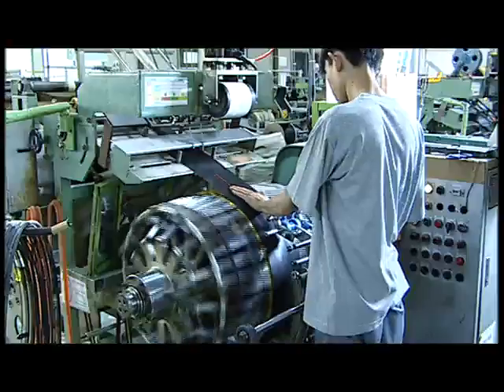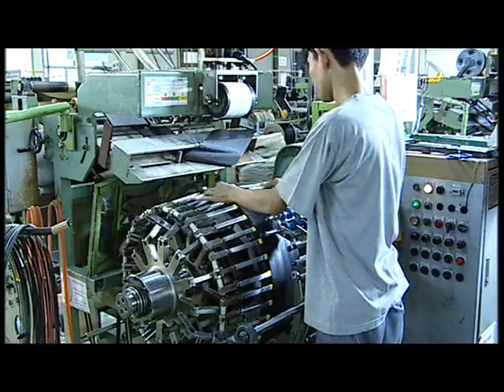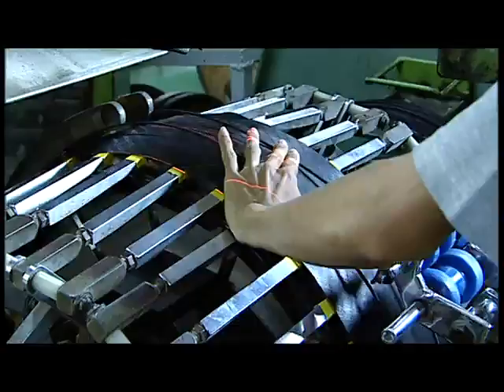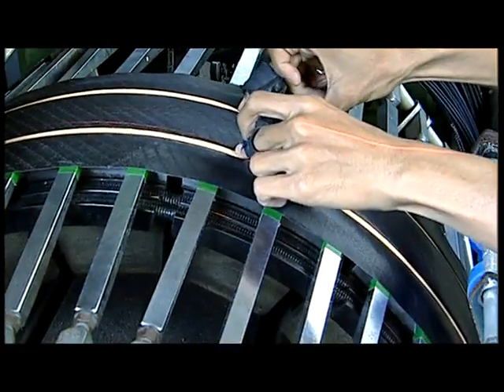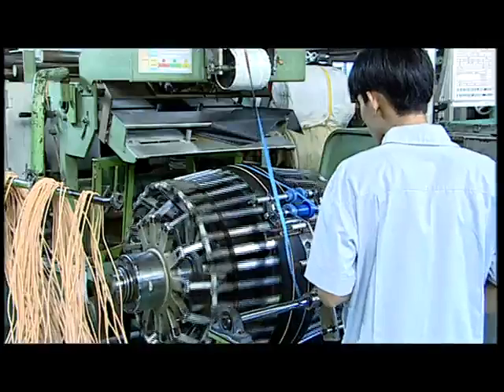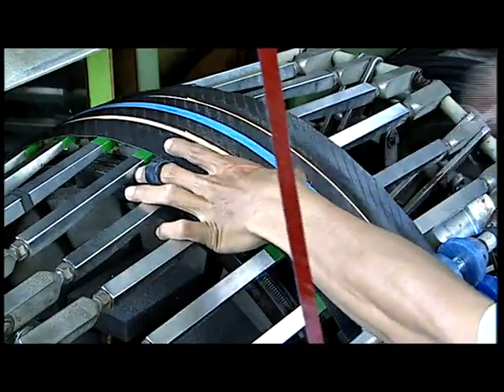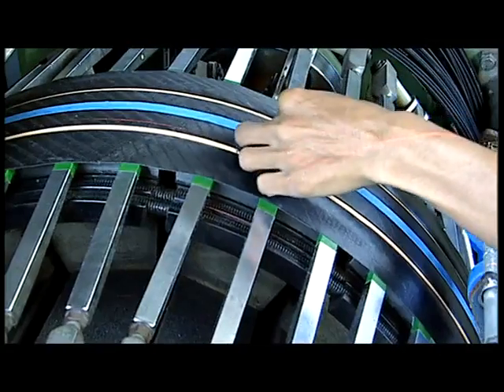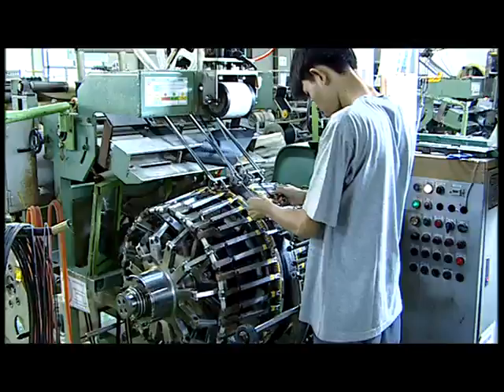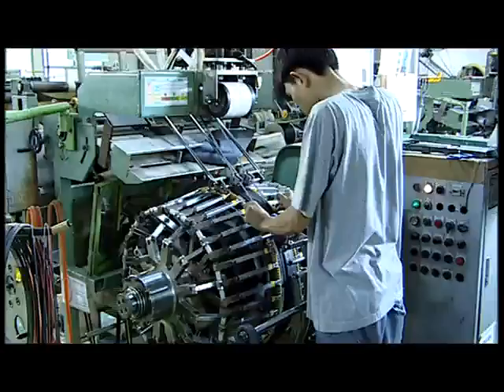All of the pre-prepared materials are now combined to form individual tires. This is highly labor-intensive work, not surprisingly assisted by state-of-the-art machinery. The carcass is laid up, cut and joined. Then the wire beads are inserted and covered by the carcass. The 45-degree threads of the carcass material now lie on top of each other, forming a tire that has a diagonal structure. With folding tires, instead of wire, a flexible aramid bead is inserted. The appropriate puncture protection layer is inserted, and centering lasers are used in all build steps to precisely position the materials. Additionally, the tire bead gets a further protection layer.